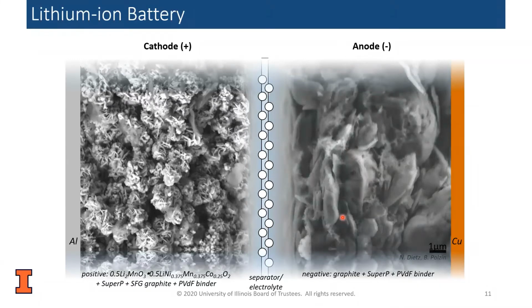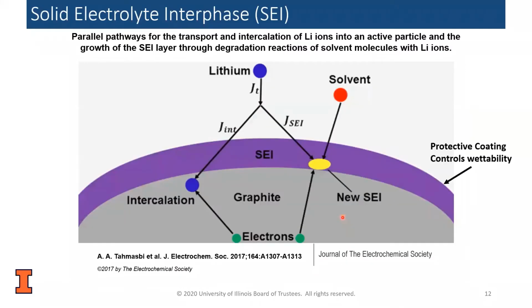Okay, so one part of the concept of the battery I'd like to introduce before I begin is what's known as the solid-electrolyte interphase. And so this is actually very key in the performance of the battery. So like I said, we'll be looking at transition-metal oxides today. And so these oxides will have a hydrophilic type surface. And so the SEI allows the oxide surface to build up a layer, an interphase that is, that somewhat mimics the solvent so that the lithium can move easily in and out. It also protects the coating and controls the wettability.